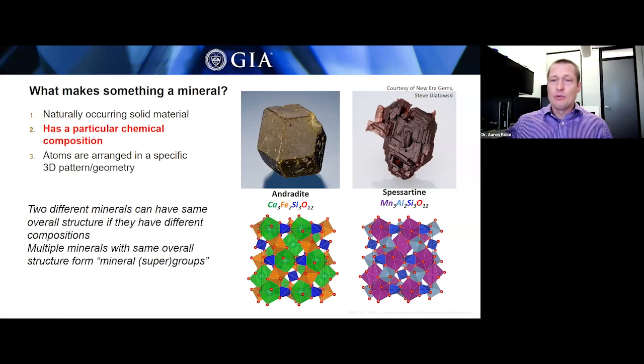These are two garnets in what we call the garnet group. And you can see from their structure below, they have very similar atomic arrangements in terms of the different types of polyhedra and the topology of the way those atoms are arranged and related to each other. But they are distinct minerals because, for instance, in this big, what we call a dodecahedral site, shown in green for andradite, we have calcium and we have iron in the octahedral site, whereas in spessartine, we have manganese in that big dodecahedral site and aluminum in that octahedral site. And so this difference in chemistry, the difference in the atoms we're putting in that overall similar structure, is what makes these two different minerals belonging to one mineral group.